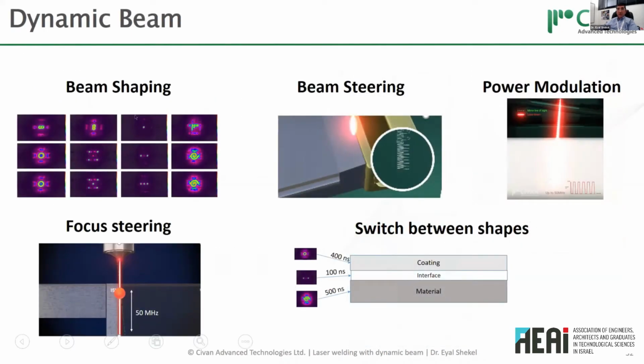So our dynamic beam can do any arbitrary beam shape. We can do beam steering. So we can basically move the beam around, and you can move the beam either at gigahertz speed, which effectively is like having some kind of a beam shape, or we can do it at kilohertz, which is really steering the beam inside the melt pool. So for example, over here, you can see you can do any arbitrary shape. For example, for welding two dissimilar materials, you can deposit a different amount of energy in one material than in the other material. We can change the focus, so you can focus the beam in the depth of the material. We can do power modulation, like we showed before, controlling the melt pool to have a sputter-free weld.